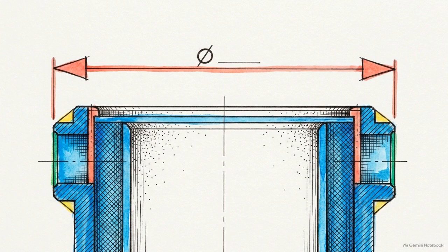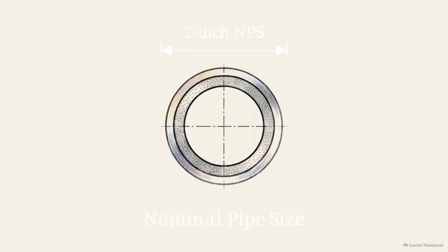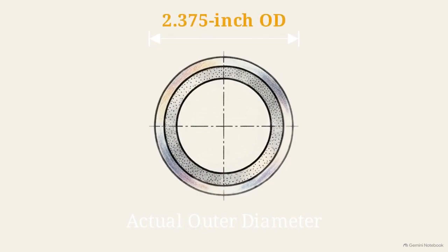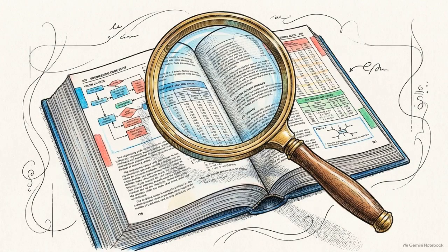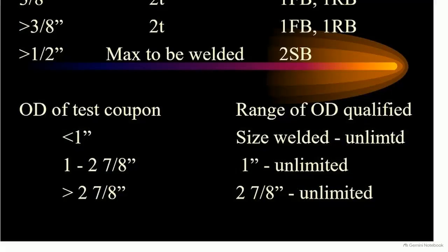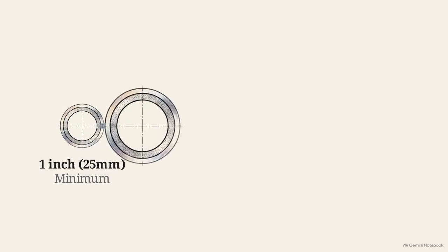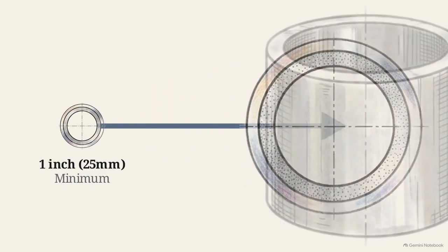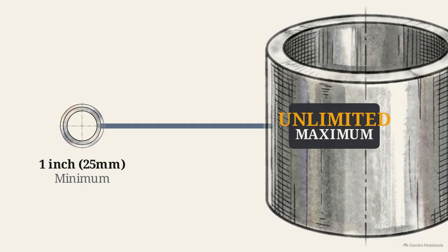The starting diameter for our coupon is 2-inch nominal pipe size. It is important to note that NPS is a naming convention. A 2-inch NPS pipe has an actual outer diameter of 2.375 inches. We must check the code to see what a 2.375-inch test qualifies for. In the lower section of this qualification table, we find the row for test coupons between 1 inch and 2 7/8 inches. Our pipe fits this tier, qualifying the welder for any production pipe with a minimum diameter of 1 inch up to an unlimited maximum.